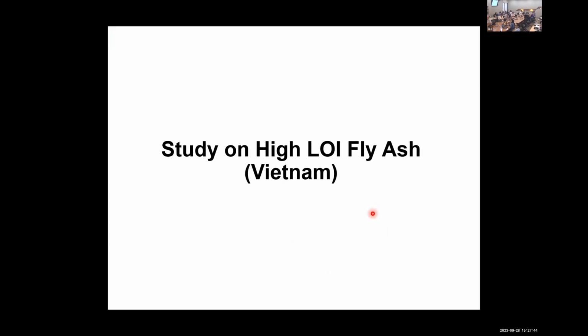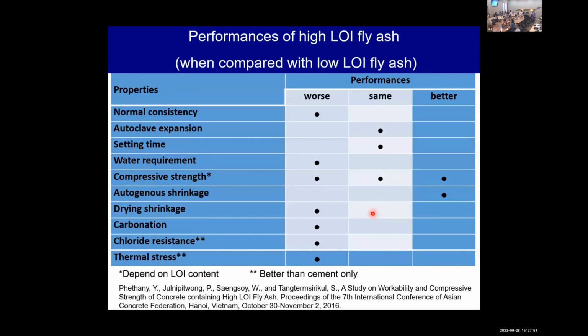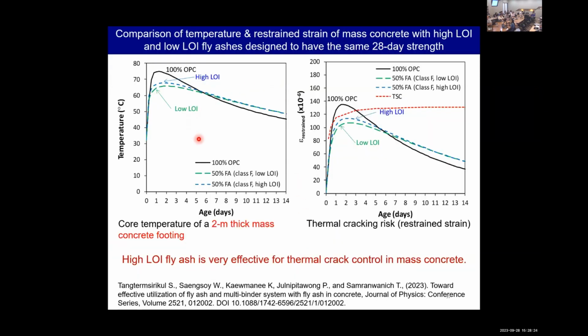And the last one is a study on high LOI fly ash. Actually, this is a problem from Vietnam, not Thailand. We also studied some properties. They compared low and high LOI fly ash, and the results show that high LOI fly ash can produce higher strength if we properly optimize or adjust the mix proportion. And even though high LOI fly ash is worse than low LOI fly ash, it is still better than OPC only, especially for the properties of temperature and thermal cracking.